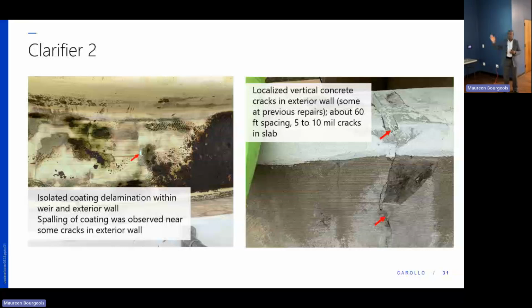Well, there's the good news, the petrographic examination, no ASR was observed. We talked about ASR earlier. All the 3 cores we looked at here, no ASR was observed. Under the microscope, 0.16 to 0.2 inches of concrete was deteriorated. So the clear cover was 2 inches. We have a little bit to spare with. And so we are recommending the coating again.